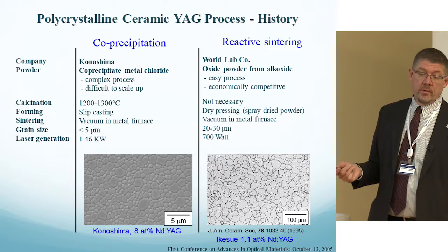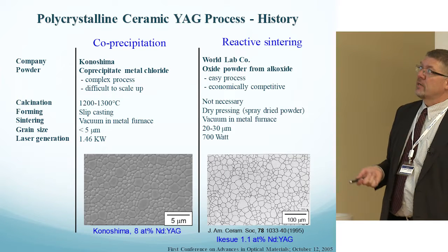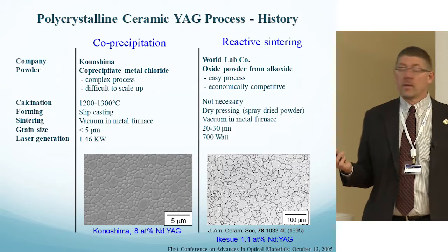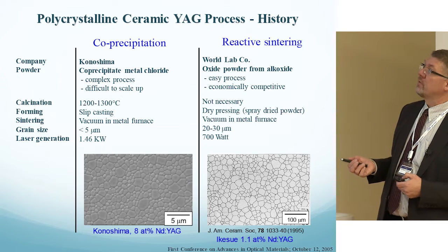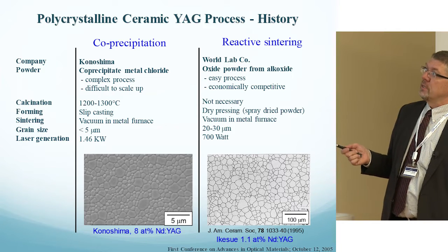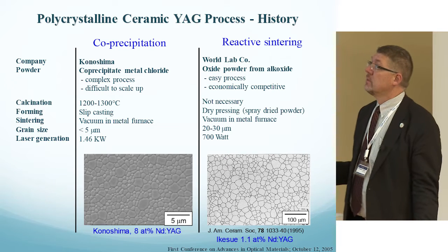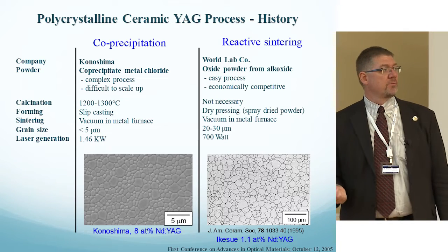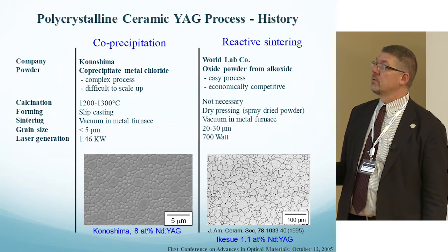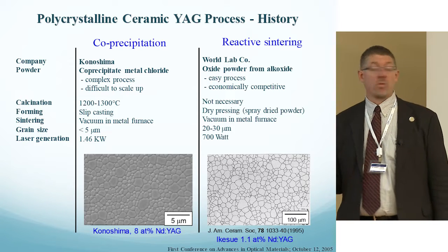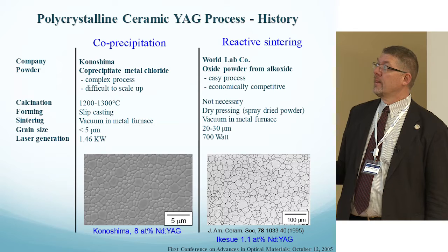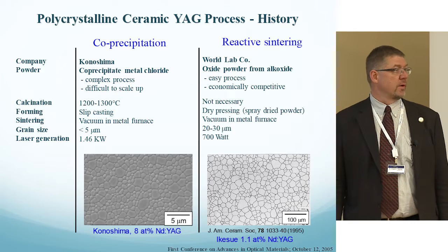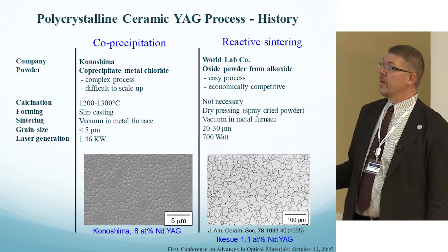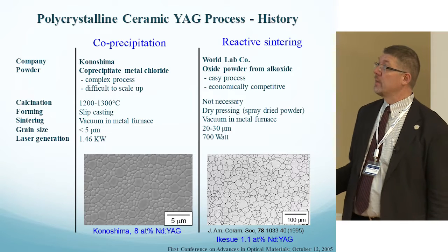There are several ways that groups have found to manufacture. Conventional sintering has been one of them. I'll show you two of them side by side here. The Konoshima team is using chemical co-precipitation. They're starting with metal chlorides. It's a complex process that they go through. It's difficult to scale up, but they are demonstrating material with very high doping, zero pores, minimal pores, very high quality, generated in laser rods over a kilowatt and a half very easily. Their grain size is about 5 microns or less.